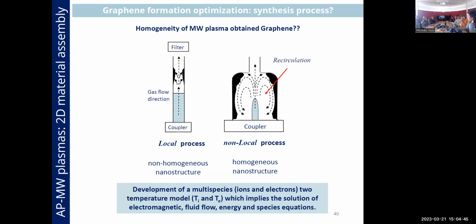Just to finish, I would like to highlight something. Imagine that this is the plasma contained in the quartz tube generated with the surfatron, and here with the plasma torch, we have the reactor. The solid material is deposited in the quartz tube walls and also in the quartz reactor walls. However, the quality and the kind of material is different in both cases. Here we have pure graphene material, and in the case of the surfatron, we have a mixture of graphene and carbon nanotubes.